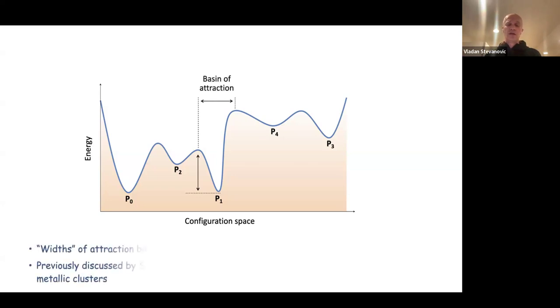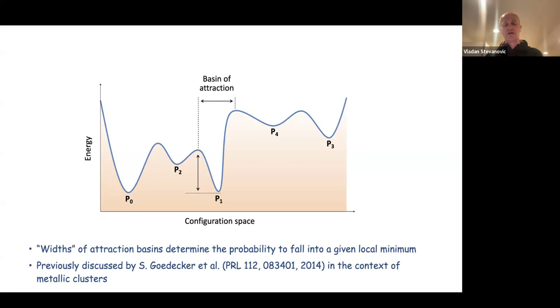So the quantity that I'm going to discuss that has to do with the likelihood of getting into different local minima is not the depth of a local minimum, it's actually the width of the local minimum, or the more mathematically precise formulation is the volume of configuration space occupied by the basin of attraction of that local minimum. Why would that quantity have anything to do with the likelihood to realize a certain polymorph? Well, the width of the local minima would measure the probability to fall into that local minimum. And the initial hypothesis that we made was that those that are wider, meaning have higher probability to fall into, will then be experimentally more realizable than the others.